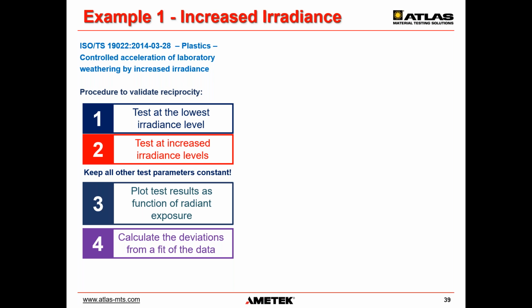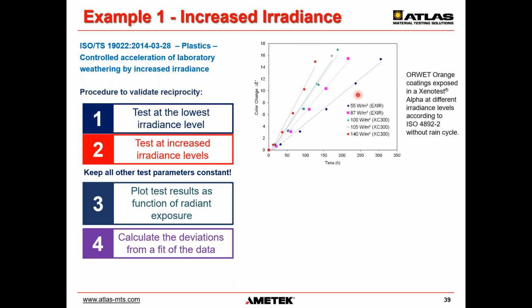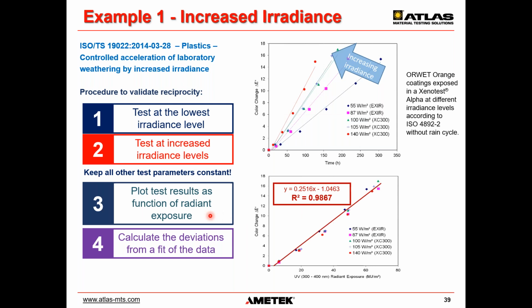ISO Technical Specification 19022 defines a process by which reciprocity can be validated. It's a relatively simple four-step process. First, test at lowest irradiance level, then test at increased irradiance levels. Here you see 55, 87, 100, 105, 140, different irradiance levels. Then plot the test results as a function of radiant exposure and not as a function of time. And then all these points fall together to one straight line in this case here.